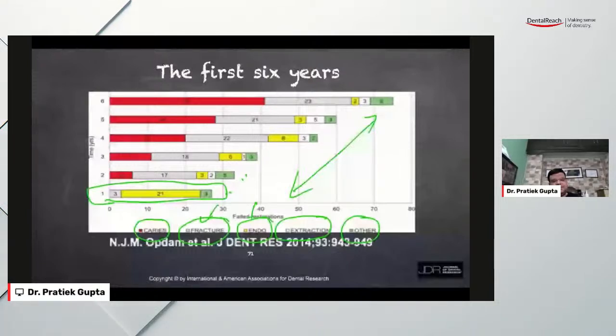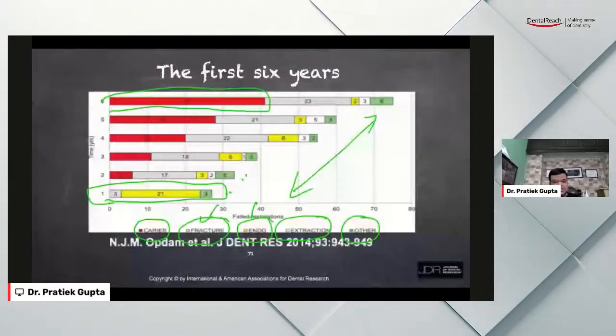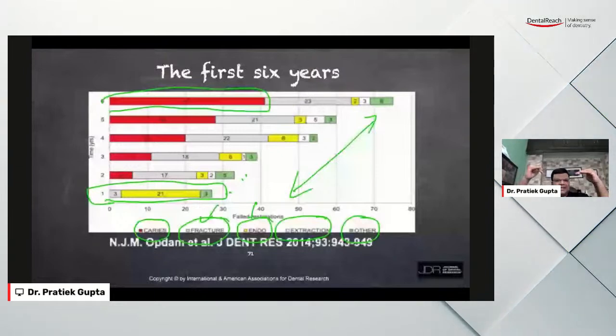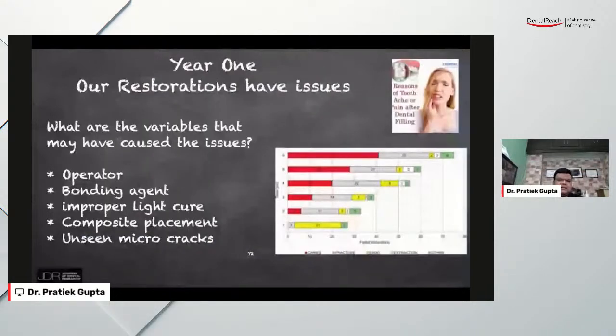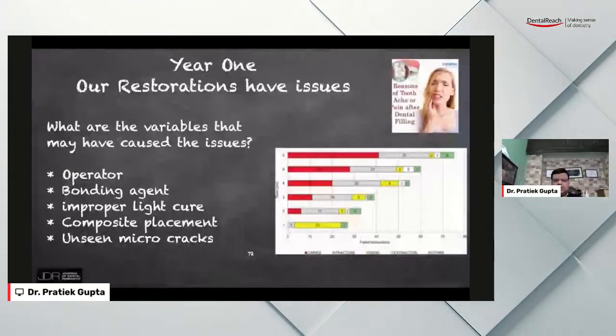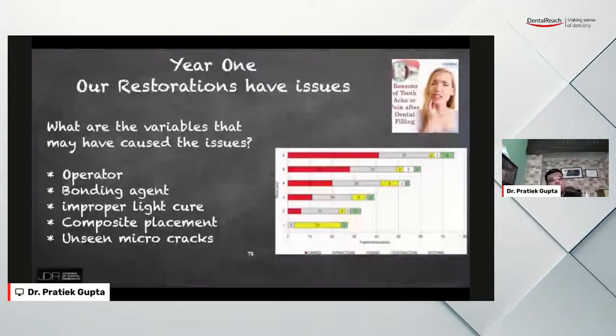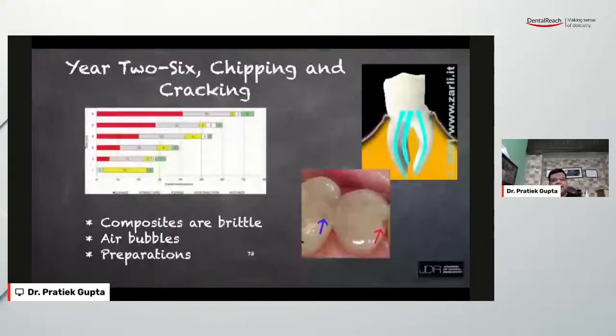But after a 6 year period, when you see the failures, and a lot of them failed, about 70%, in that about 41%, the failure was caries. What does this mean? Like I said, around the margins, biofilm formation starts, moves inside, and that leads to all the problems. In the first year, it is probably because of the operator, because of the bonding agent, because of light cure, because of not noticing micro cracks. Year 2 to 6, you have more chipping and cracking that happens.